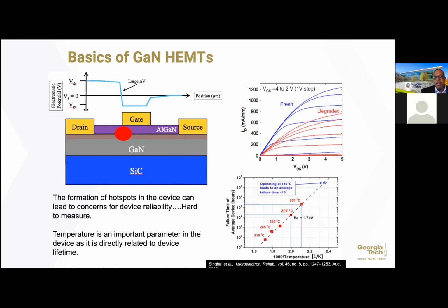So again, here's my image of my hotspot that occurs right here at the drain side edge of the gate. As I said before, I may have to grow this on a non-native substrate, something like silicon carbide. People have chosen this because of the high thermal conductivity of silicon carbide, being on the order of about 400 watts per meter K versus about 180 for GaN. And so we're going to look at heat dissipation that moves from this region down through the substrate. But again, there's a lot that has to be done right here at this interface in order to make this work.